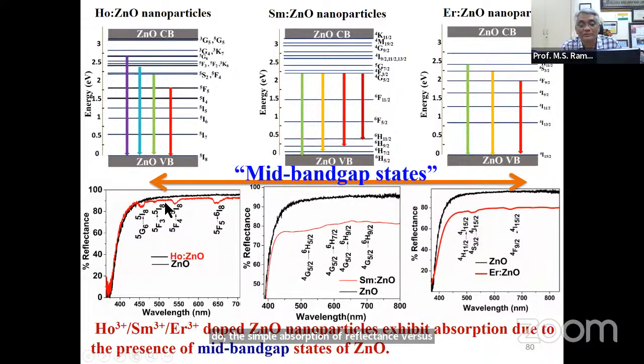It's more clear in the case of holmium - I can even identify the levels corresponding to those absorptions. This is wonderful, proof enough that holmium is going inside the zinc oxide lattice. And then we made microspheres out of this holmium doped zinc oxide.